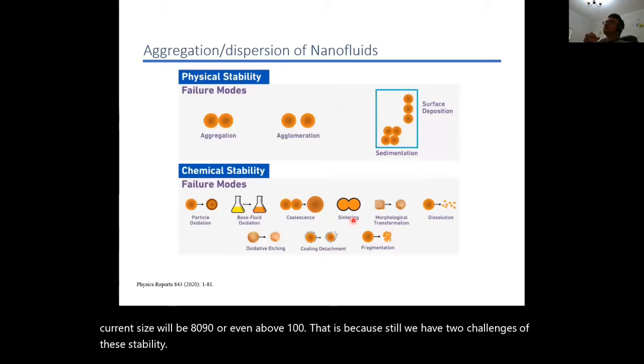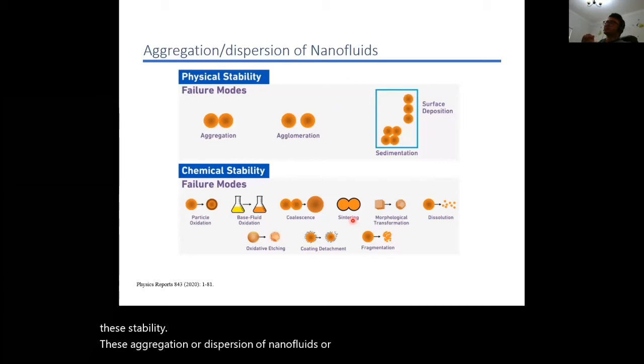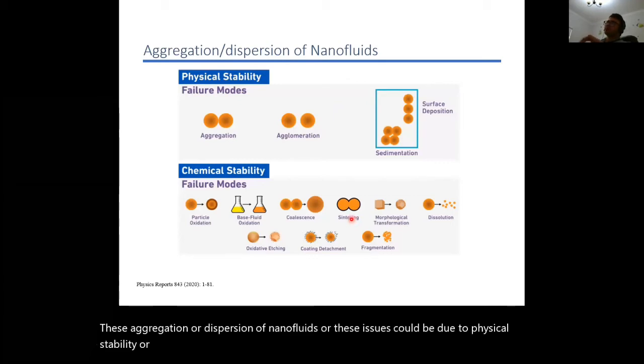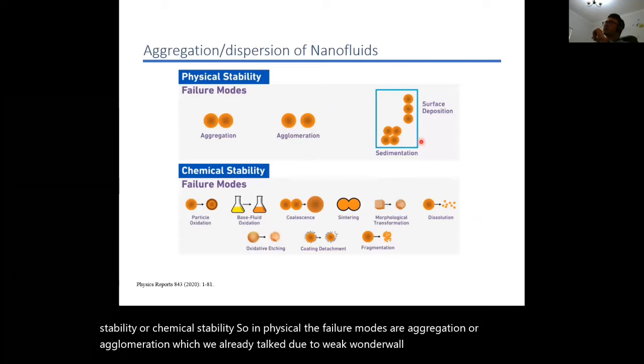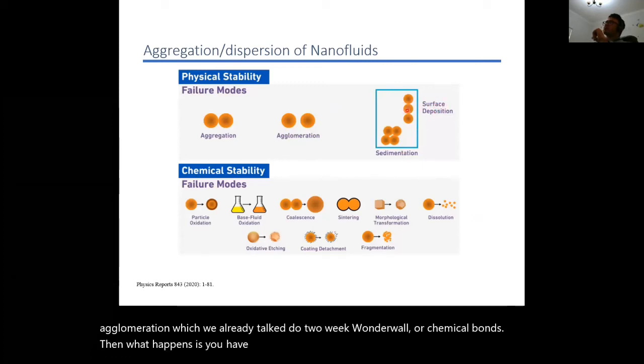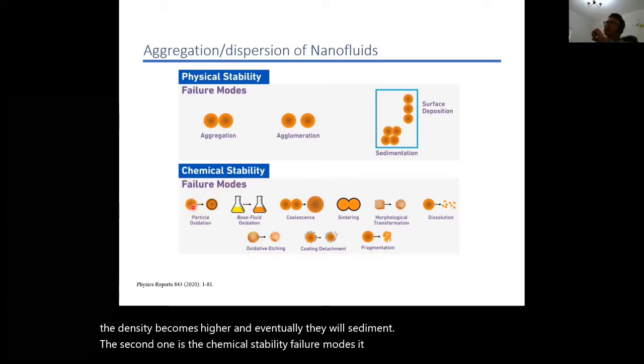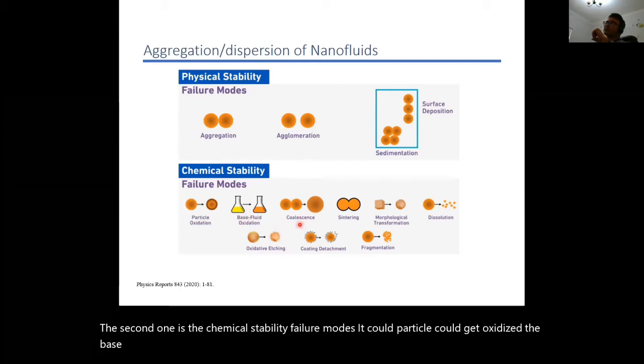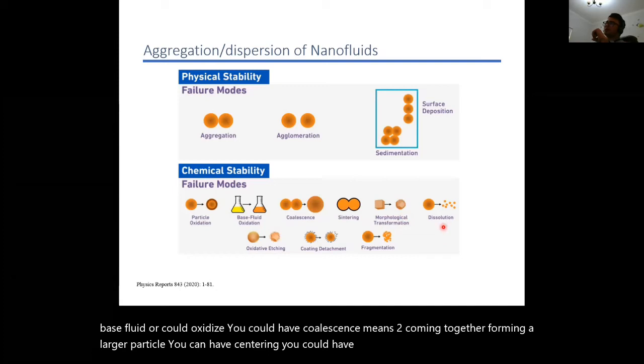These aggregation or dispersion issues of nanofluids could be due to physical stability or chemical stability. In physical, the failure modes are aggregation or agglomeration, which we already talked about, due to weak van der Waals or chemical bonds. Then you have surface deposition, and once they come together, of course, the density becomes higher, and eventually they will sediment. The second one is chemical stability. Failure modes: the particle could get oxidized, the base fluid could oxidize. You could have coalescence, meaning two coming together forming a larger particle. You could have sintering, morphological transformation, dissolution, oxidative etching, coating detachment, or fragmentation.